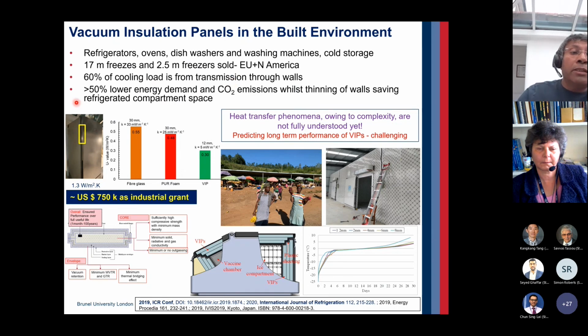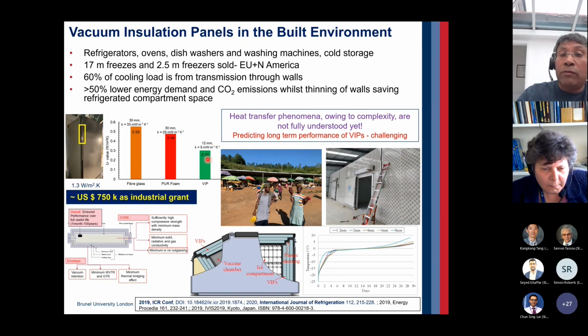The example here is that a normal fridge has walls up to about 60 millimeters thick, because the insulation inside is very thick. But we've shown that only a 12 millimeter thick VIP could bring down the U value of the wall from 1.3 watts per meter squared to only 0.3. So clearly, a huge amount of space could be saved within the refrigerated compartment by using systems like VIPs. We're currently working on a grant of about 750K US dollars for developing vacuum insulation panels for a variety of applications within the built environment.